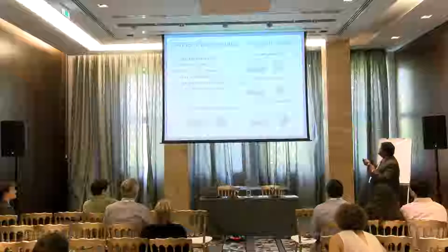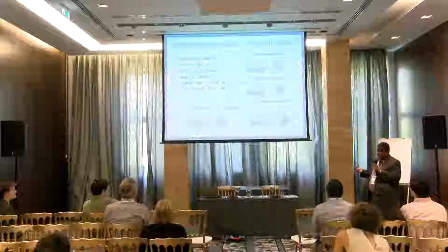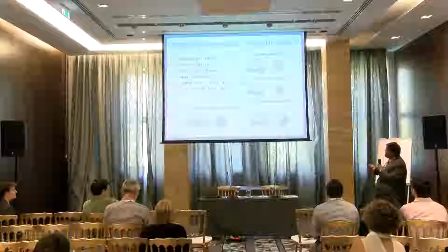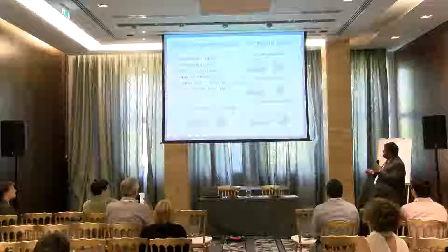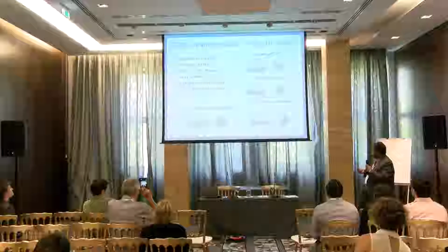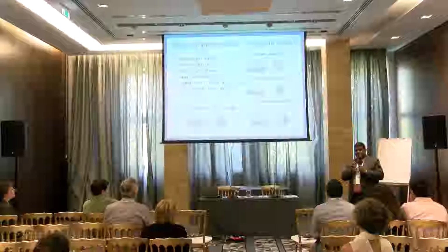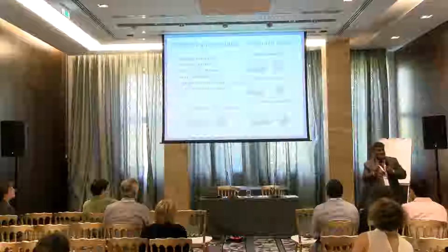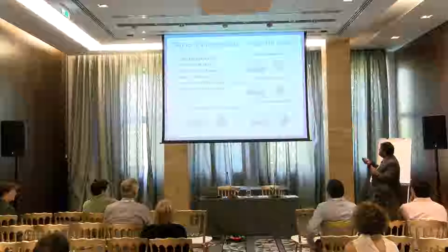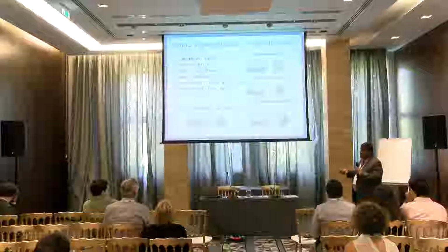So we have used 4 different types of projectiles, which are very standard for this kind of low velocity projectile impact, starting from a flat nose. Then we have a round nose, a conical nose, and the 4th one is a conical frustum. The projectile type has a significant effect on the damage mechanism at the point where the projectile impacts the fabric. It depends on the flatness, roundness, and sharpness, and this one is in between.